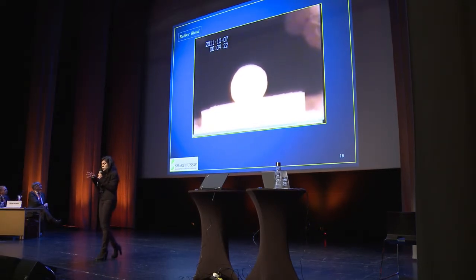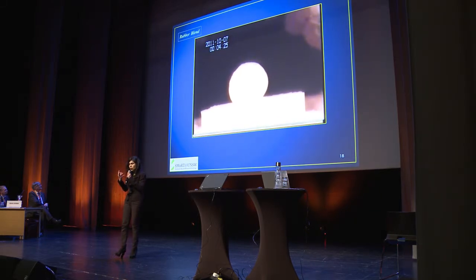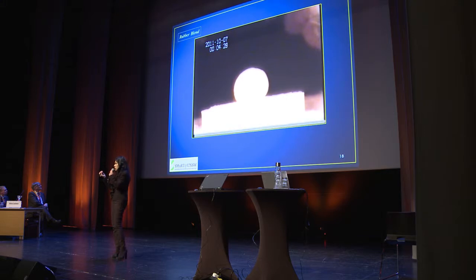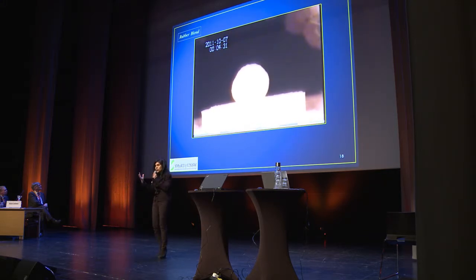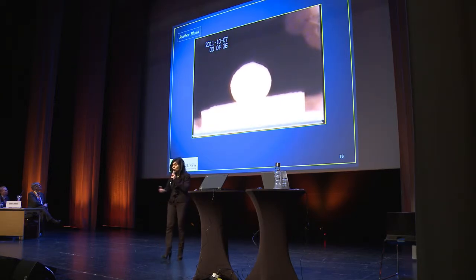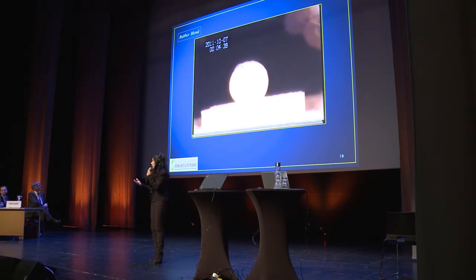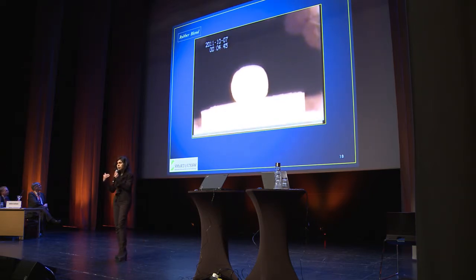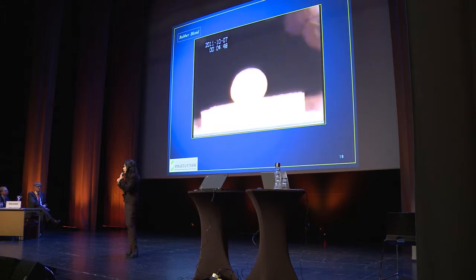So if you look at it carefully, you will see indeed, of course, that bubbling action going on, the gas bubbles being generated, and of course, they're able to be sustained within the slag, therefore giving the kinds of benefits that you would expect a good slag foaming to actually deliver in commercial furnaces. And that's exactly what we have seen, that in commercially operating furnaces, we see better performance when we've actually used a blend of rubber and coke as an inject material into our furnaces. Now, of course, as I showed before, the presence of hydrogen molecules is very efficient, allowing us, of course, to see these kinds of benefits. So that's really ultimately the critical question.